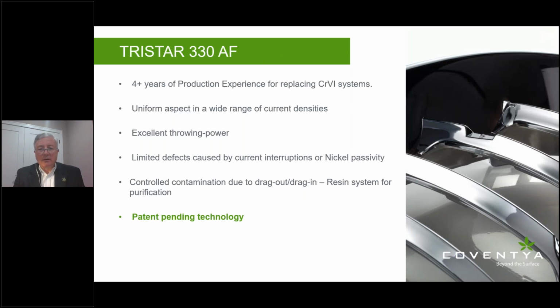So in a quick summary of where we are, we've got 4+ years of production experience. And again, Alberto Chiappa will talk about that in our replacement of chrome 6. It's got a very uniform aspect, wide range of current densities, which is very beneficial for a lot of complex parts. It has excellent throwing power. The distribution is very good over current densities. We have limited defects, by current interruptions or other types of racking issues. We can control the contamination through a resin system, purification system.